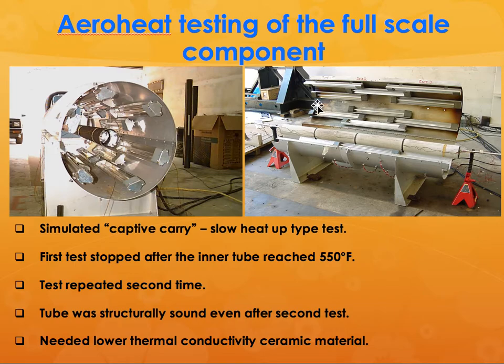We tested that in an aero heat type of a structure. So we put the tube inside this and we heated the outside up to say 1000 degrees centigrade or whatever. And the first time we did that, the inner tube reached only 550 degrees Fahrenheit. So we stopped the test and then we repeated the test a second time. And even after the second test, the tube was still structurally sound.